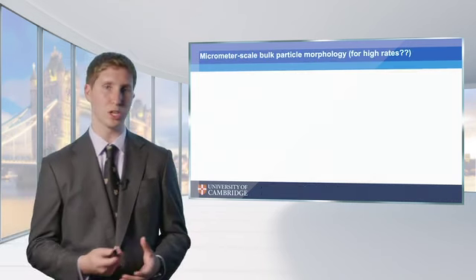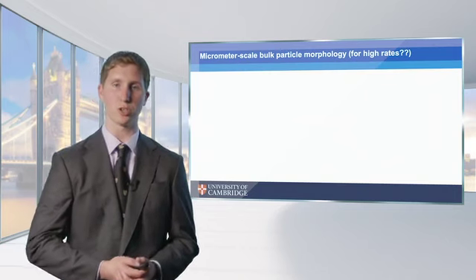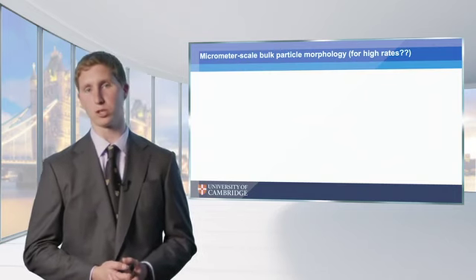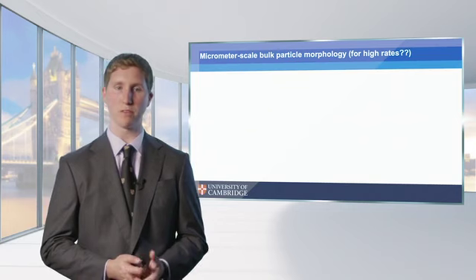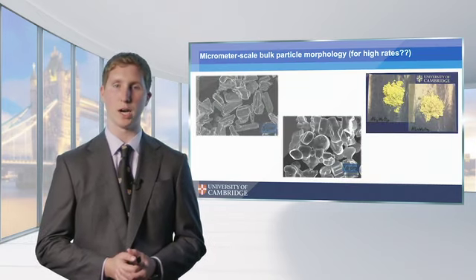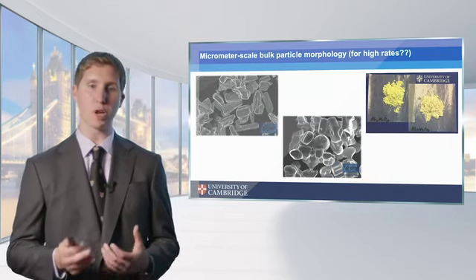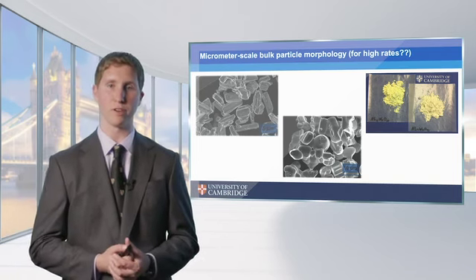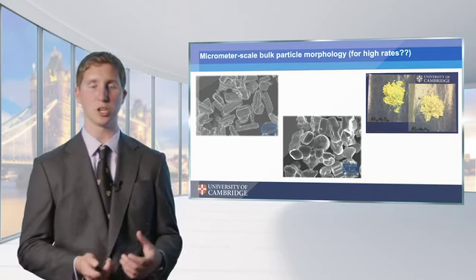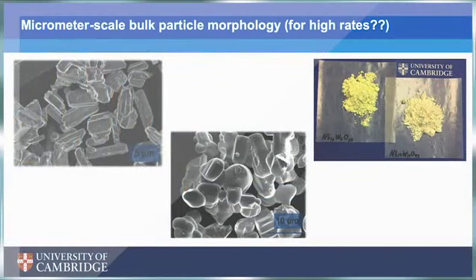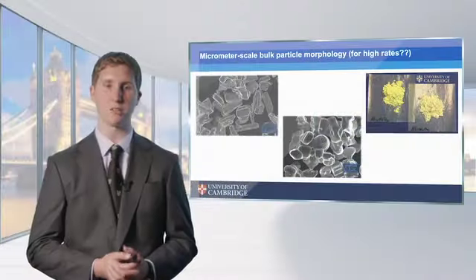And so once we understand something about the atomic scale structure, then it's also important to think about what our microstructure is like. And so conventionally, when we're working with high rate materials or trying to do very, very fast charging, fast lithiation and delithiation, we think about going to the nanoscale because we decrease the diffusion distances required. But there are some disadvantages with going to the nanoscale in terms of our ability to cost effectively synthesize the materials and process them, and reactivity down the line.